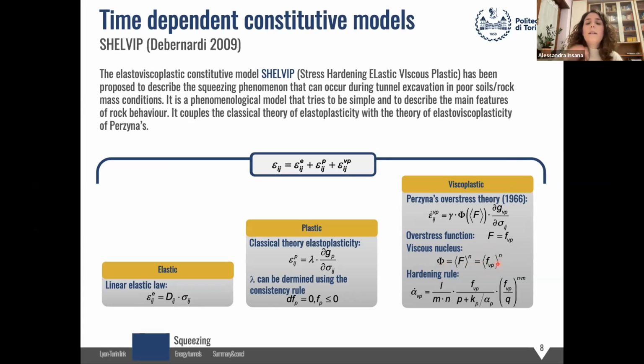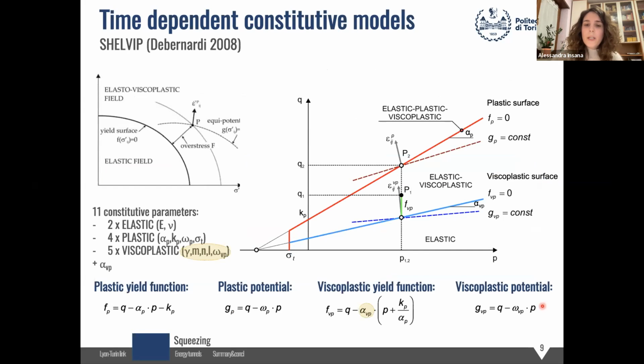And the aspect of novelty of this model is the hardening rule. So the viscoplastic yield function is not fixed, but it can harden thanks to this rule. So in the triaxial stress space, we have two yield surfaces, the viscoplastic one, which is based on a linear Drucker-Prager criterion. So alpha_P and k_P are the intercept and the slope with the q axis, and a plastic surface.